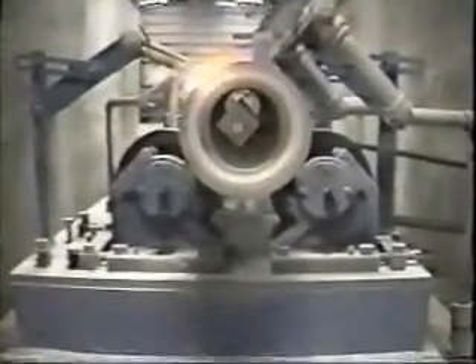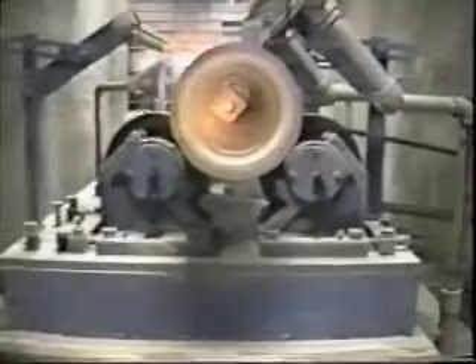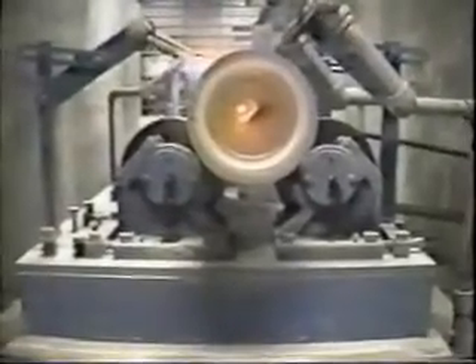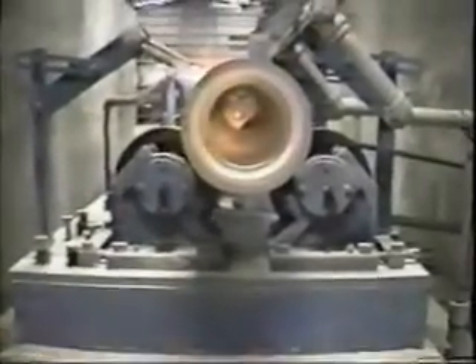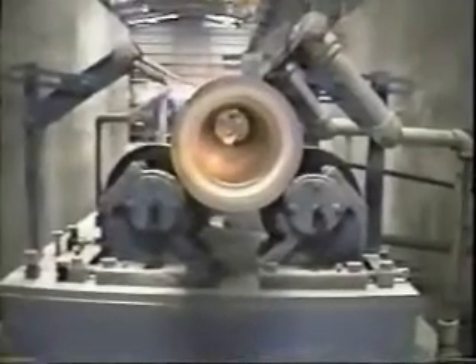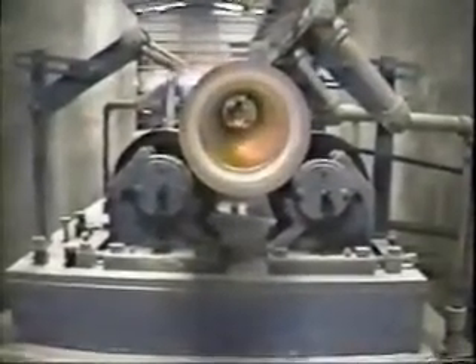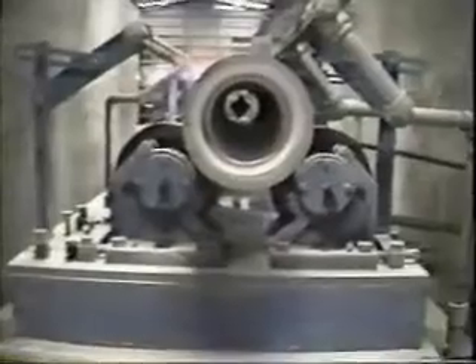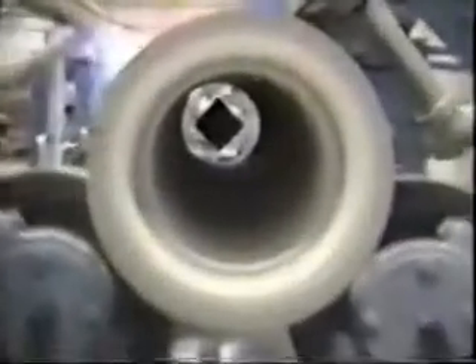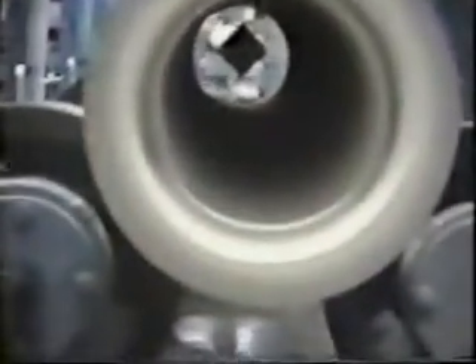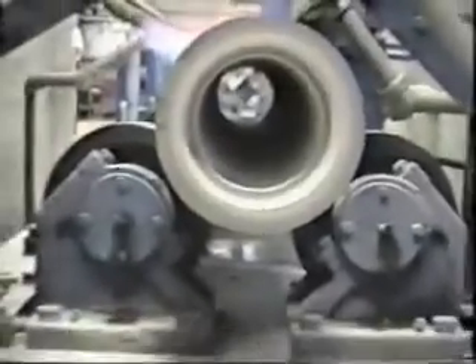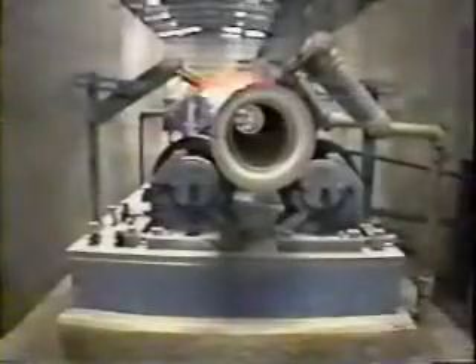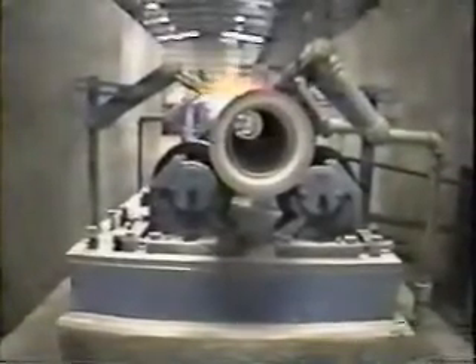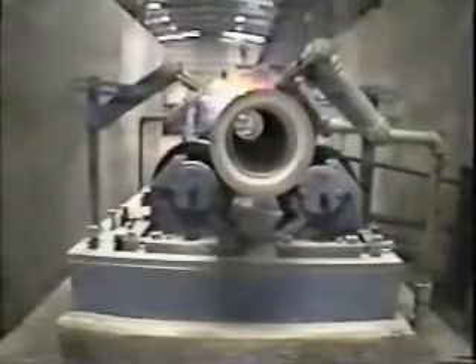The mold is a shorter mold, approximately 7 feet in length. It's being coated again with the same lance, 3 passes, but the end rings are left off in this case because of the smaller diameter. This is to maintain the mold temperature while the mold is being coated and the metal prepared.